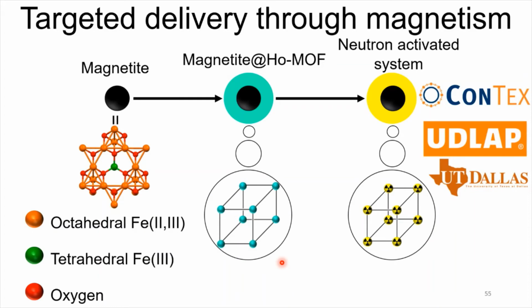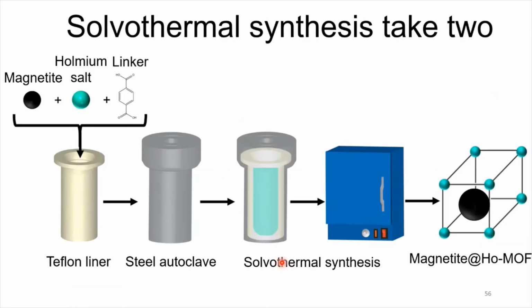And we actually got a grant from ConTex. ConTex is a participation between University of Texas branches and Mexican universities. So we got the grant to start working on this. And the synthesis is really as simple as this. Once you get the magnetite, it's basically the same synthesis conditions that we've been working through. The only difference is we are trying to find how the magnetite itself affects the synthesis conditions. And we have noticed that even if we cut the times to 10% of the original, we still see a huge increase in crystal growth.